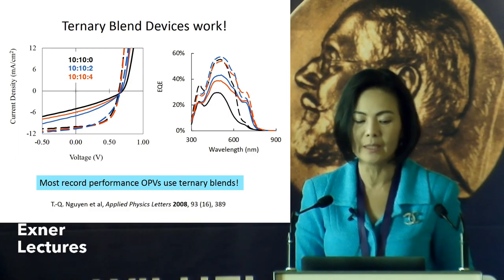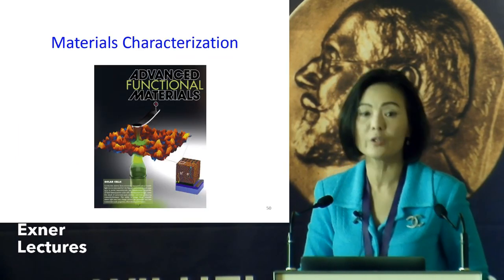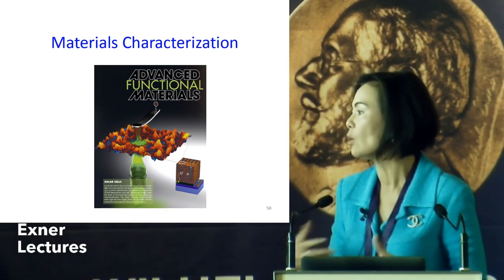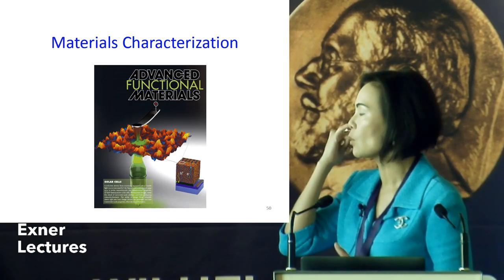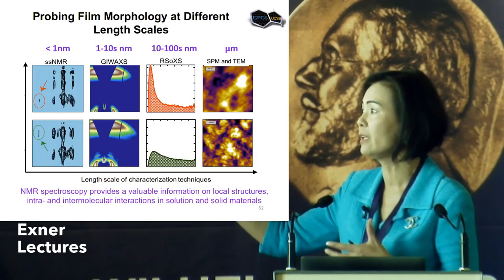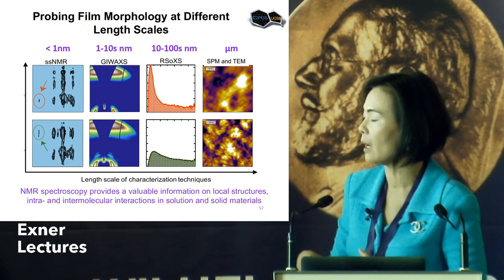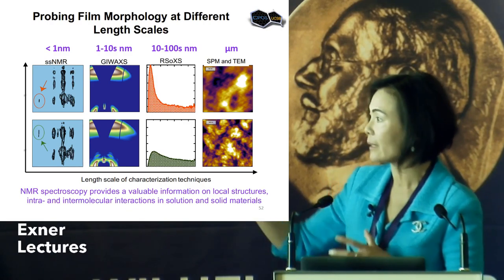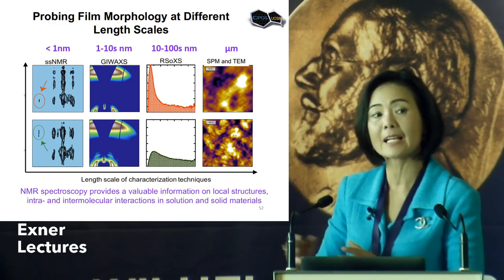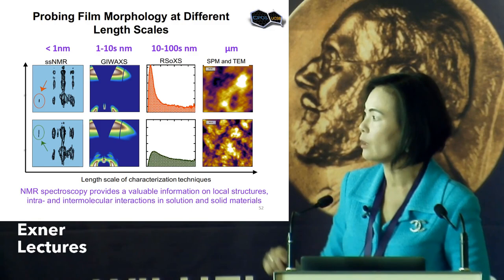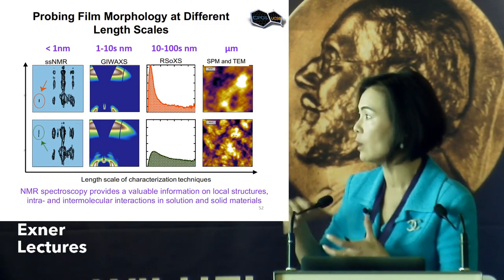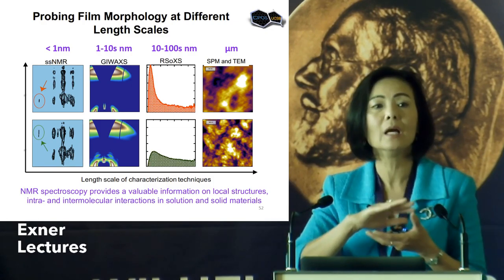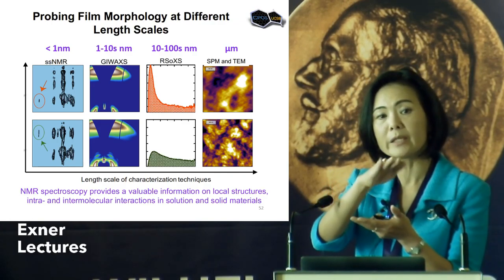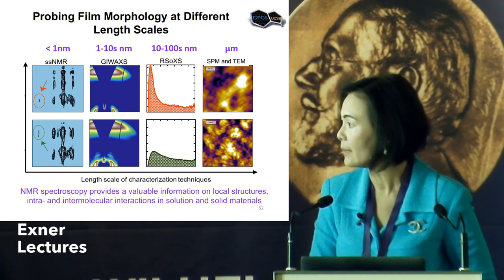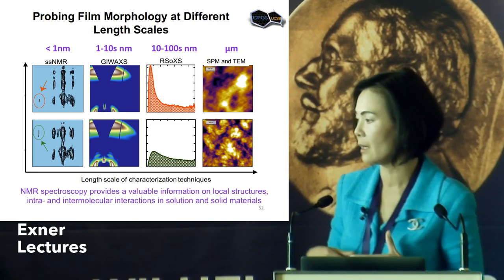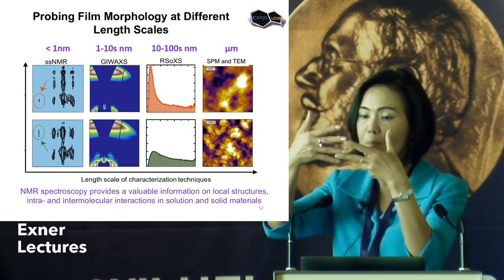So now I would like to quickly highlight another one, which is the morphology. So I mentioned already, to understand the morphology, you need to understand it on different length scales. And over the years, together with collaborators, we developed tools that allow us to probe morphology at different length scales. For example, using solid state NMR with Manju Reddy, a young professor at University of Lille, that allows us to probe at the atomic, molecular level the interaction between donor and acceptor molecules. And then using grazing incidence wide-angle X-ray scattering that allows us to look at the crystallinity, molecular order, and also the molecular orientation of molecules with respect to the substrate. And together with Harald Ade, we also apply resonant soft X-ray techniques to probe the degree of phase separation and the degree of mixing between the donor and acceptor.